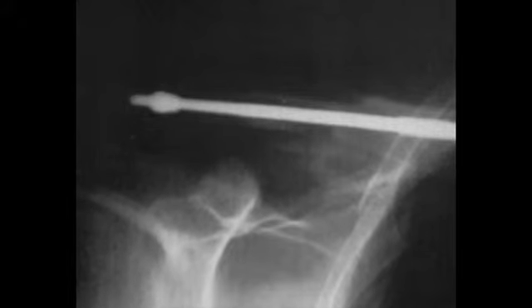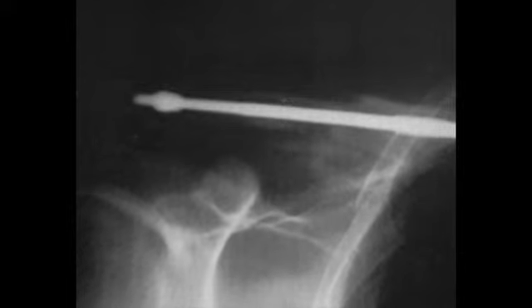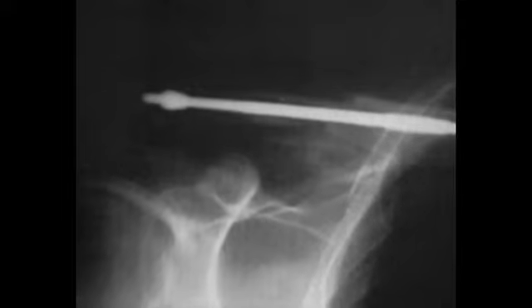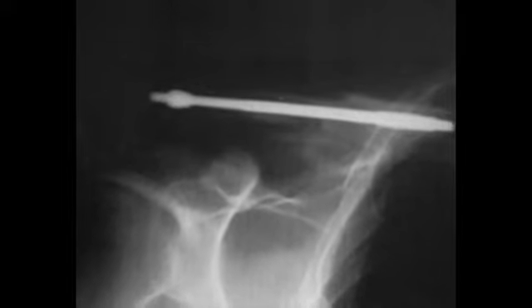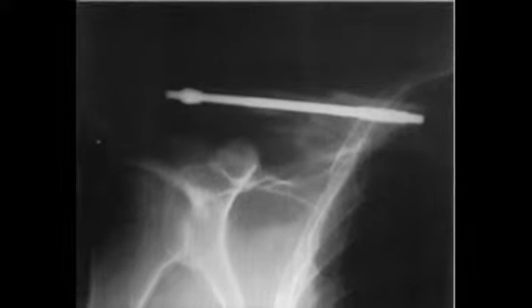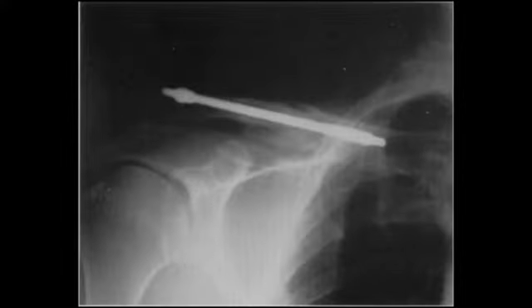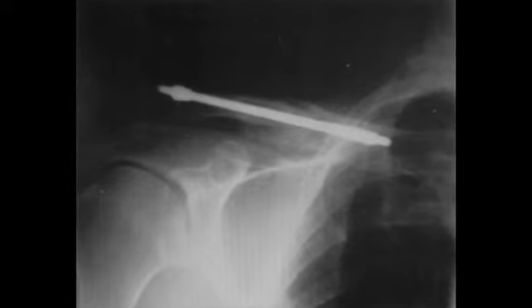Fracture fixation and proper pin alignment were confirmed intraoperatively using C-arm fluoroscopy. The hex nuts were applied to the end of the Rockwood clavicle pin and cold welded in position. After confirming the proper clavicle pin position, alpha BSM was applied to the fracture seam to assist the healing process. Soft tissues were then sutured over the repair and the surgical wound closed.